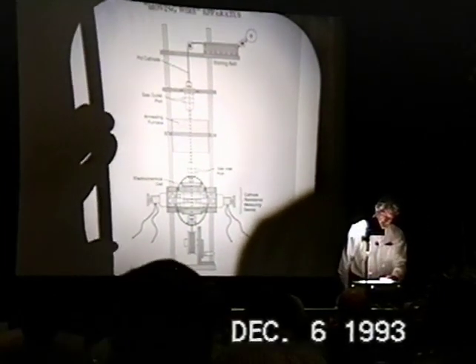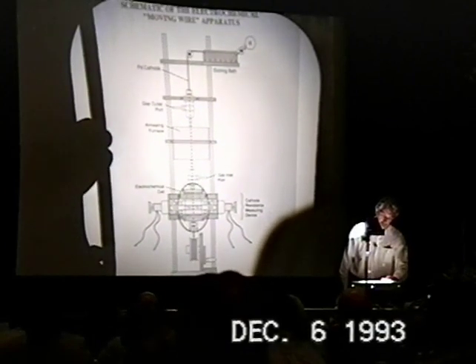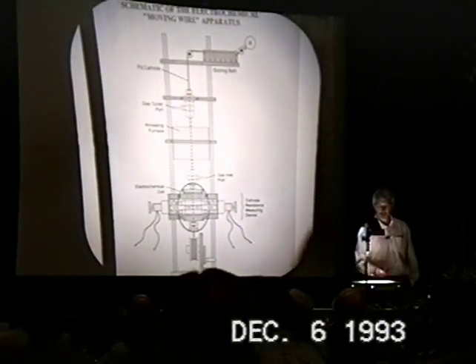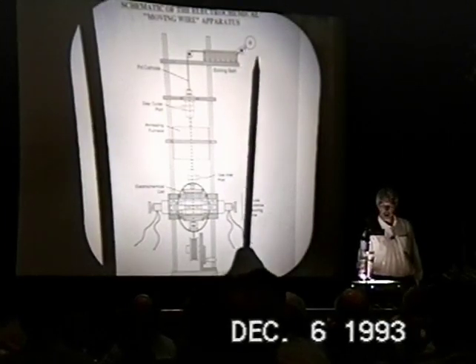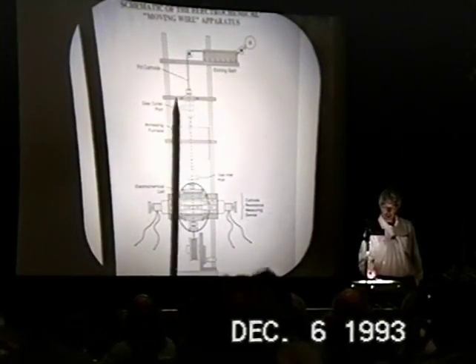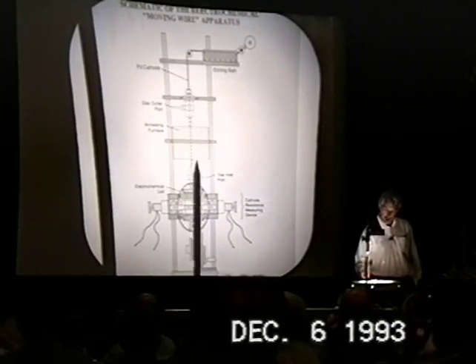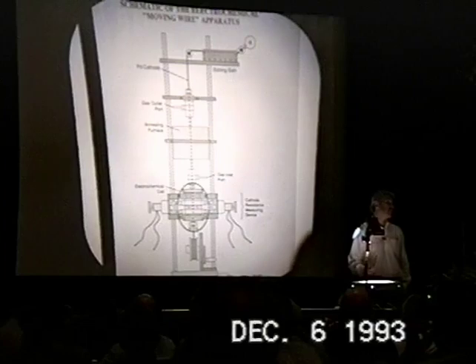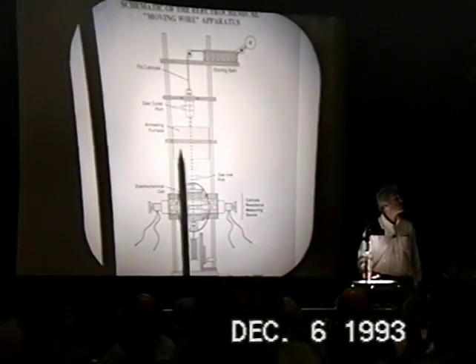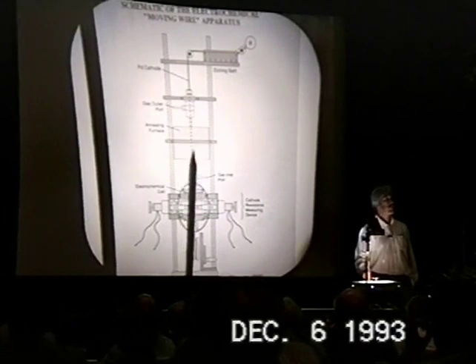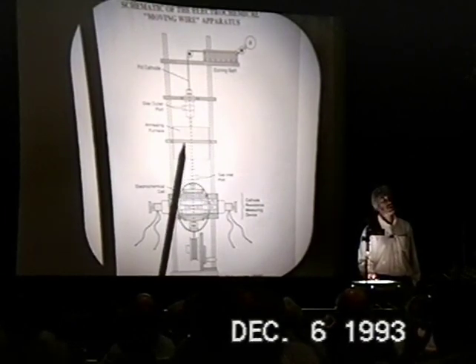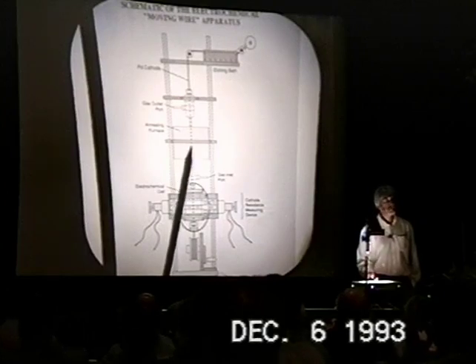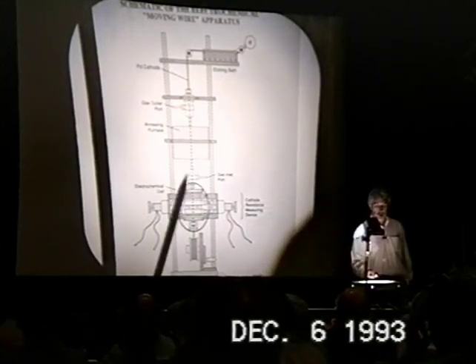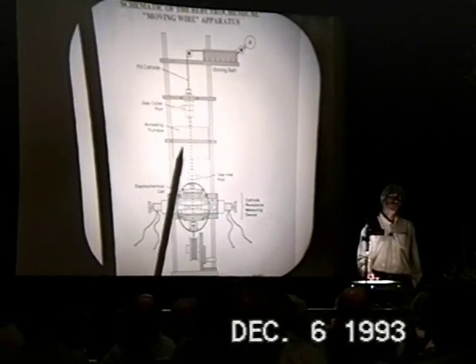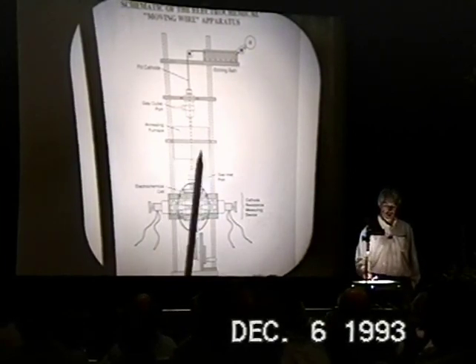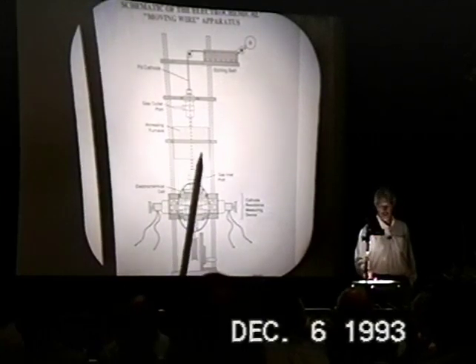I mentioned the moving wire apparatus. I want to show you a brief sketch of it. It's a movable wire. Basically, you start with a 1 meter spool of 1 millimeter palladium, which goes through an etching bath, and is conveyed down through an annealing furnace where we maintain a controlled environment and controlled temperature for programmed time to establish a uniform pre-annealing treatment of the surface. We can also pass gases through here in order to deposit species on the surface during or after the annealing process.